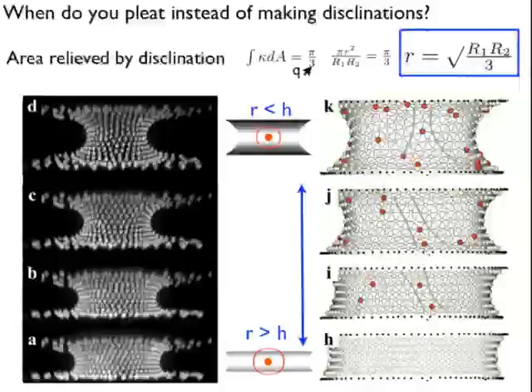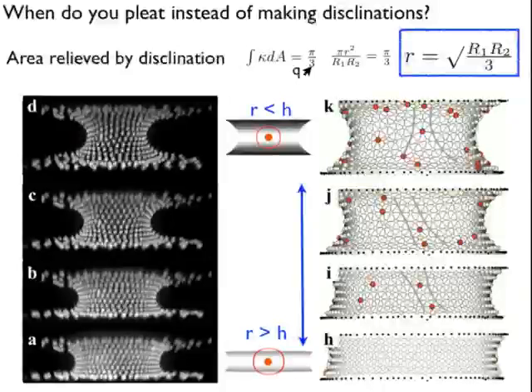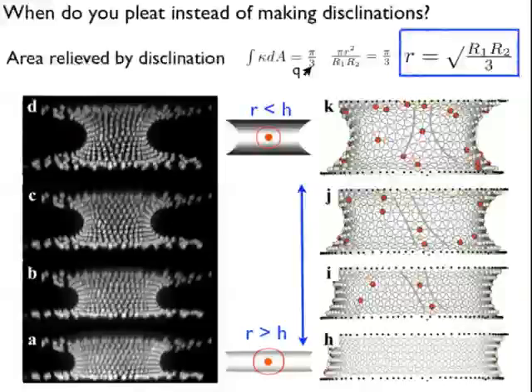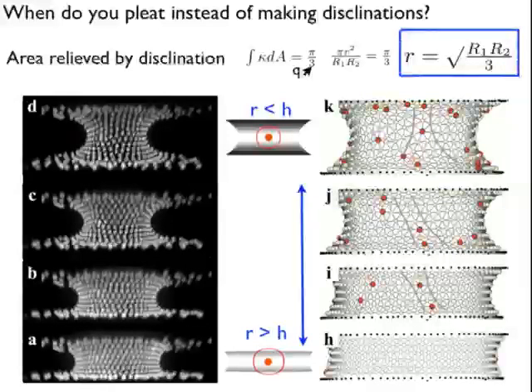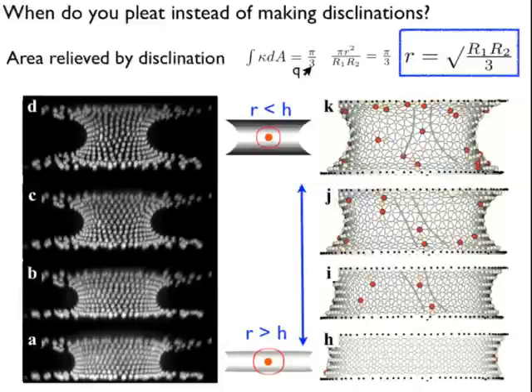And the real thing that happens in terms of whether you get pleats or whether you get disclinations is whether the boundary of the region that corresponds to this integrated area of Gaussian curvature hits the boundary or not. If it hits the boundary, you get pleats. If it's inside the boundary, you get disclinations. So that's kind of neat.